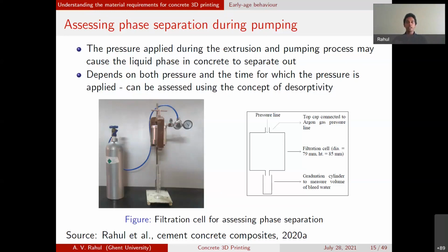On the other hand, if you're working with a screw pump, you are doing continuous batching. You have a rotating screw, and you feed the material into it, and as soon as the material is fed, it's transported to the print head, which typically takes less than 1 minute, depending on your pipe length. So the pressure you're applying is for a very short time in this case. For the piston pump, on the other hand, you have all the material placed at once inside the piston and the pressure is being applied, and the entire extrusion time, depending on the length of the piston, can be as long as 15 or even up to 30 minutes.